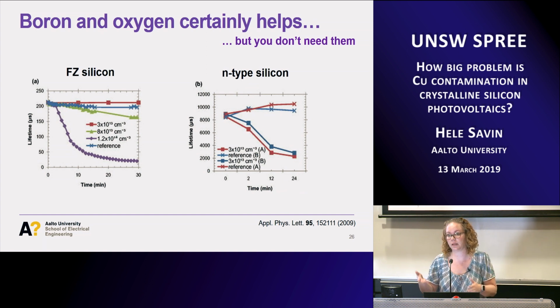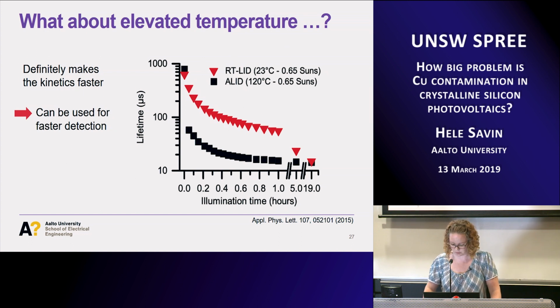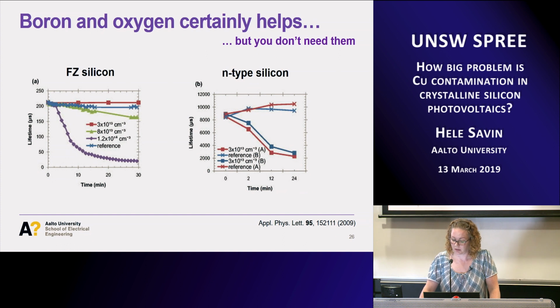Okay, the statistics is not then great, but at least we were repeating the experiment twice, just to be sure. To my recall, there was no difference. Maybe there were different vendors or suppliers, but the starting lifetime looks so close to each other that most likely not. Sorry, I cannot remember, but at least not a big difference. These are float zone N-type wafers, with relatively high resistivity because the lifetime is so high. In 1 ohm centimeter N-type silicon, copper starts to precipitate already in N-type when it has high enough dopant concentration. That's also well known.